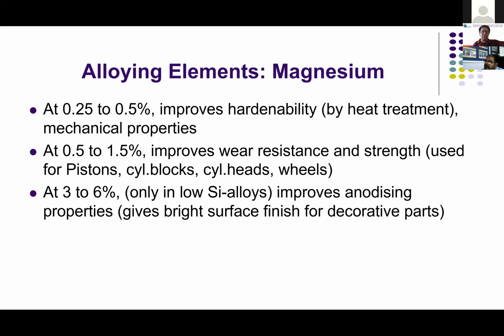I checked it up at the start of the shift. At the end of the shift, there is a drop in magnesium. So therefore, we should start with 0.35 or 0.4 in GDC and LPDC to achieve a very good hardness at the later stage in the heat treatment furnace. This is very important. You maintain the magnesium above 0.3 in the casting, not in the molten metal. In the casting, we should have more than 0.3%. Then only you will get a hardness of 95 to 110 BHN comfortably, easily.